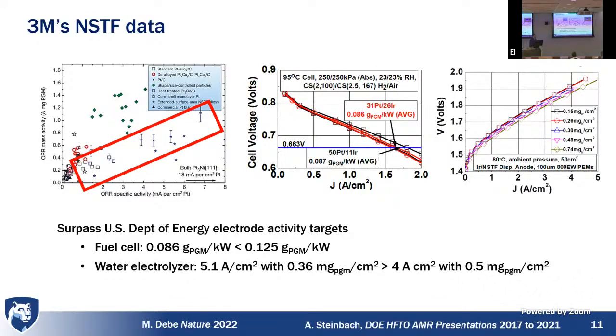If we look at the water electrolysis case, the metric is what current density can you get at 1.8 volts per platinum group metal loading. They were able to get 5 amps per square centimeter at a loading of 0.36 milligrams of platinum group metal, that would be both the platinum and iridium in the MEA. This exceeds the target of 4 amps per centimeter squared at 0.5 milligram of PGM loading. So very promising platform.